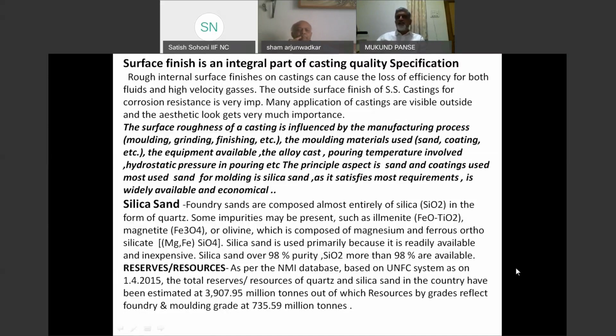Also, mainly the casting forms a small part of the total equipment, and the total equipment is of a different look. You cannot have a bad part in a total equipment which will get highlighted. Also, the surface finish of stainless steel casting is very important for corrosion characteristics. To increase the corrosion resistance, even in stainless steel casting, you are doing acid treatment on the surface. So even the small unevenness can reduce the corrosion resistance of the product.